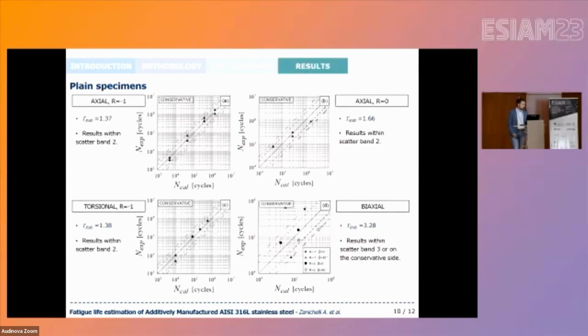Here in the present slide, the results in terms of calculated fatigue life versus experimental fatigue life are shown for the plain specimen types. And in particular, it can be observed that all the results fall within the scatter band 2, which is the dashed lines in the present graph, for both axial and torsional fatigue tests, whereas for biaxial tests, the results are within the scatter band 3.